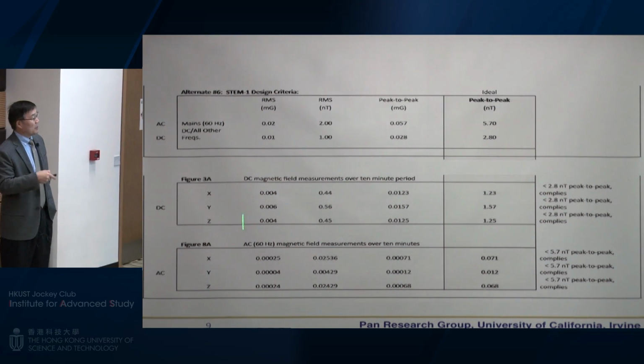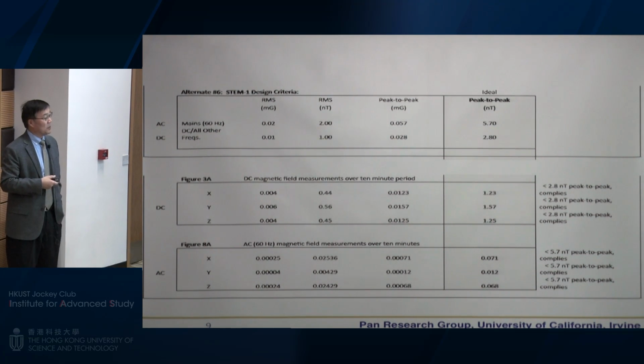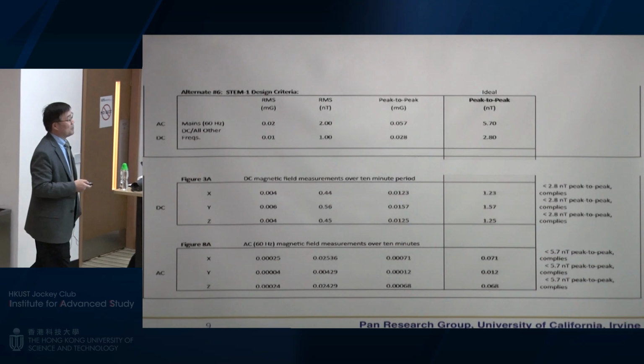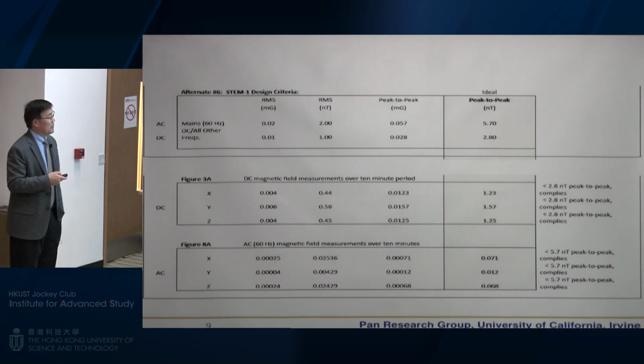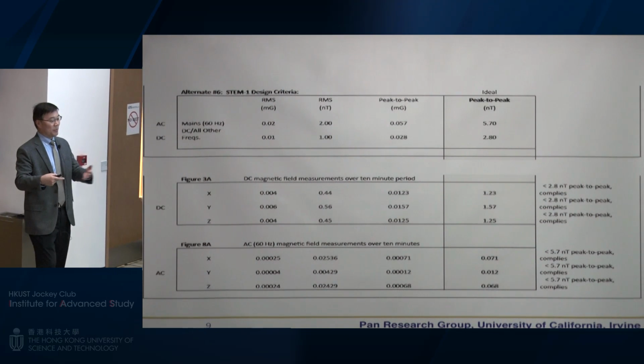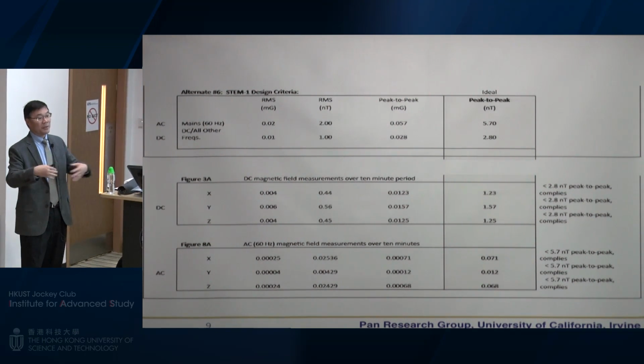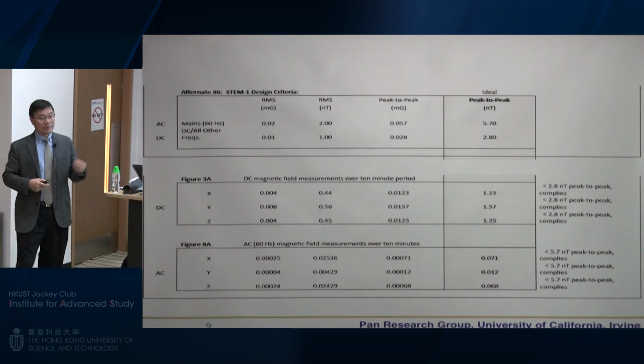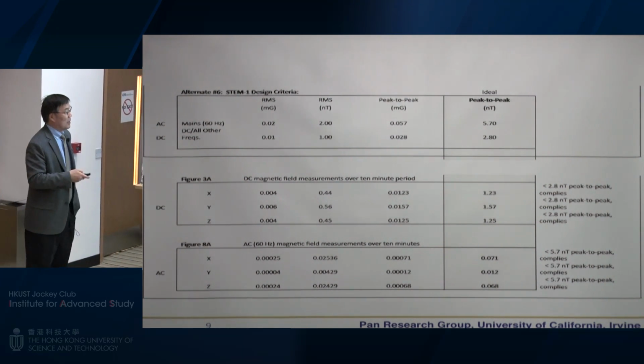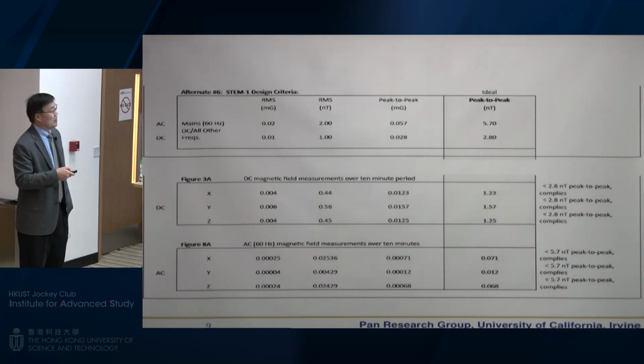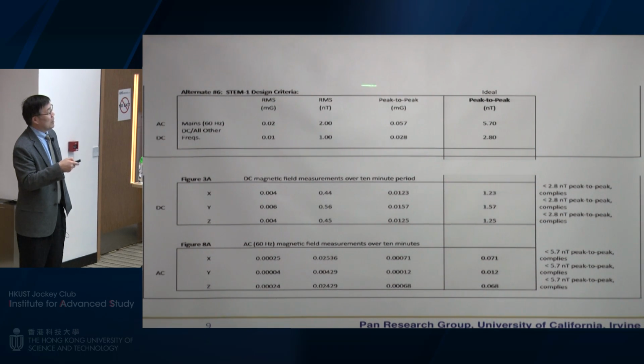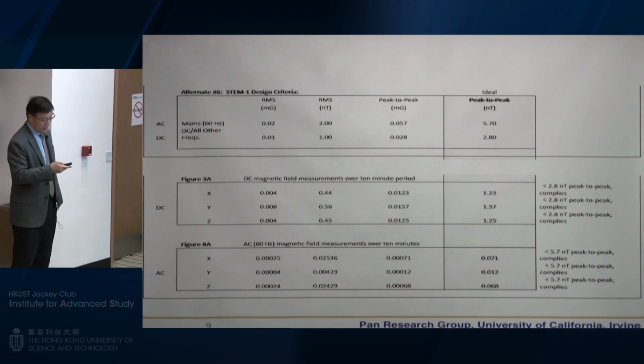The renovation project started with a bidding, and only 2 companies wanted to bid. In the end, only 1 was able to do it. They were very nervous, therefore they asked for a safety policy and asked for much more than it may cost. And eventually, if they cannot do it, they probably have to pay something back. But anyway, in the end, they did a very good job. So this is the requirement criteria. You see that the field has to be smaller than 0.01 milligauss, but what they measured is 0.004. It really worked very well.